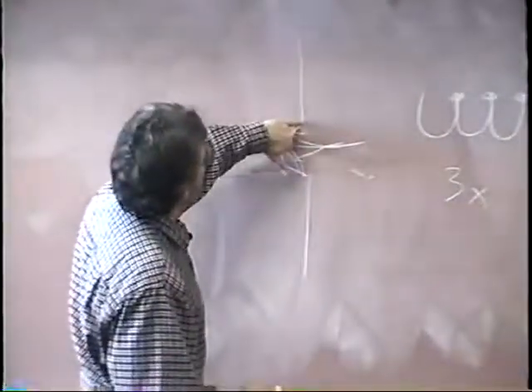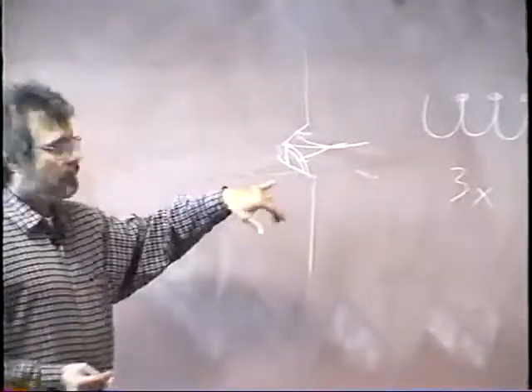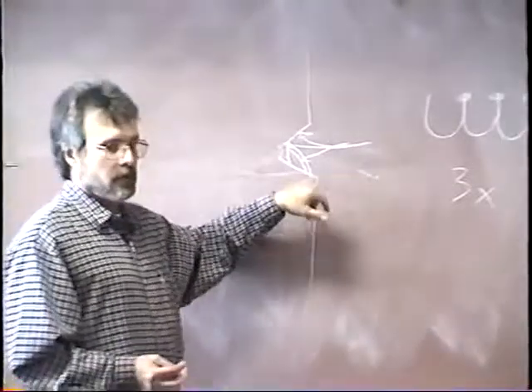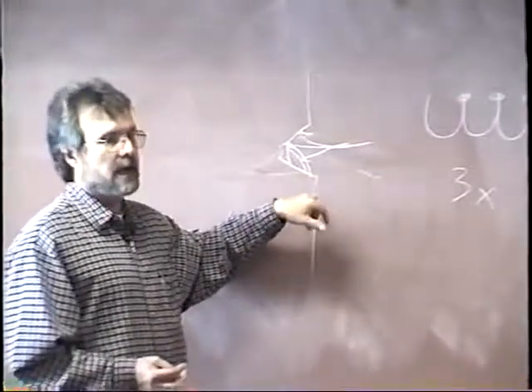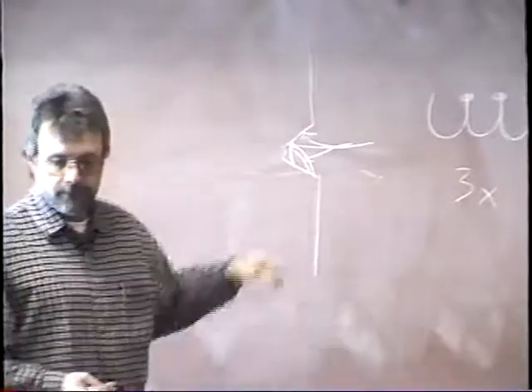When the third and fourth passes are being deposited, the arc should be kept away from the extreme edges of the pipe bevel, as they are easily burnt away by the intense heat of the arc, resulting in an undercut. Another reason you want to stay away from these nice little beveled edges until you're ready to cap it, is because you want to leave those as your road sign, as your marker, as your guide when you go to cap those off. Okay.